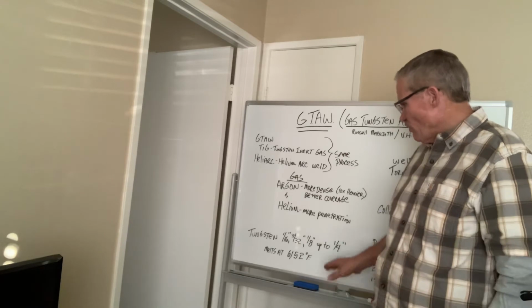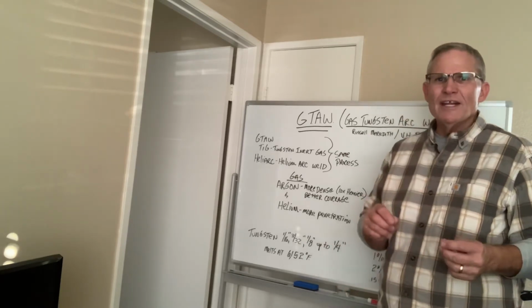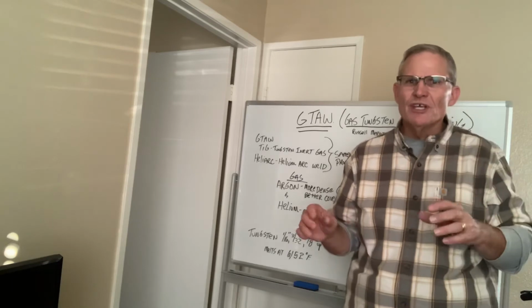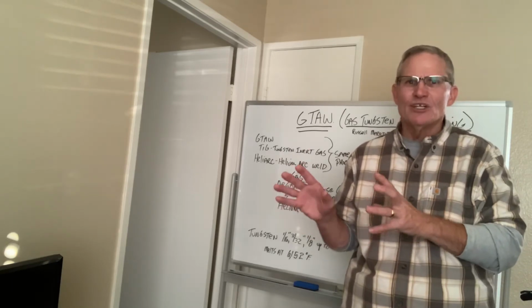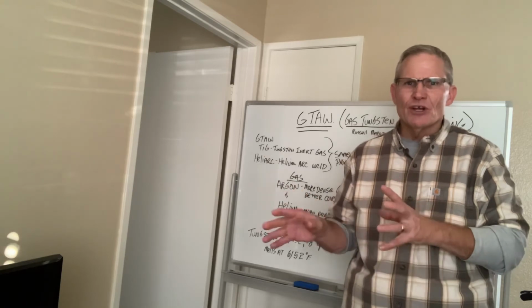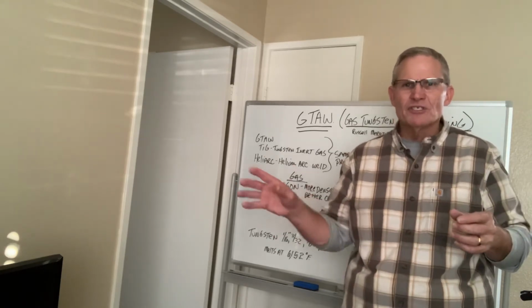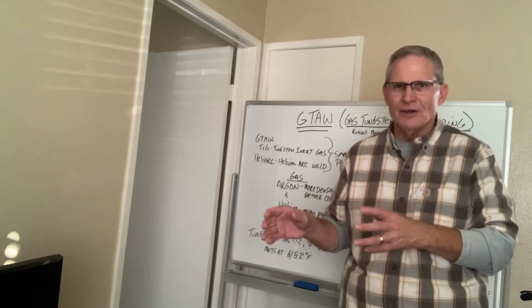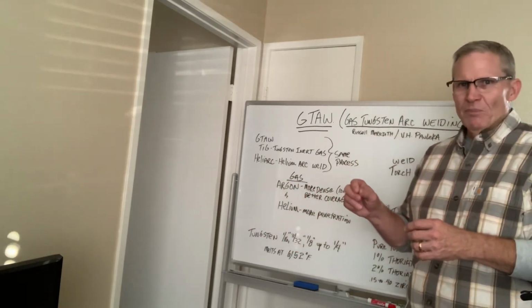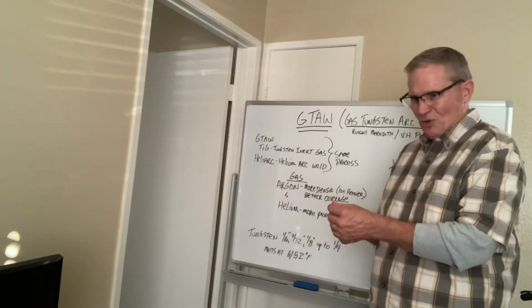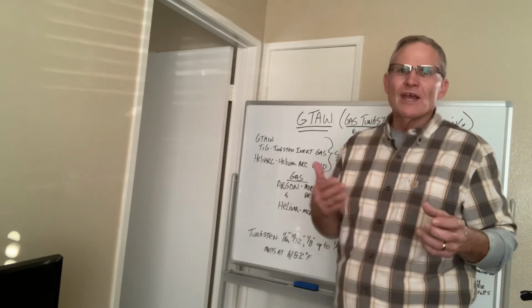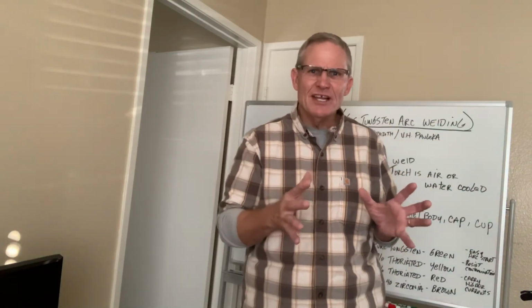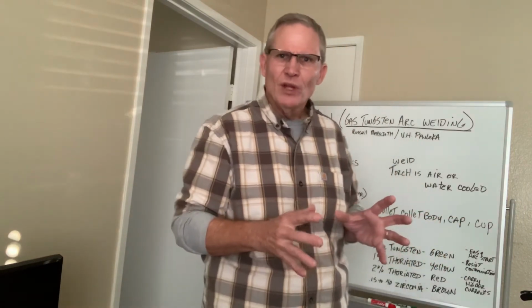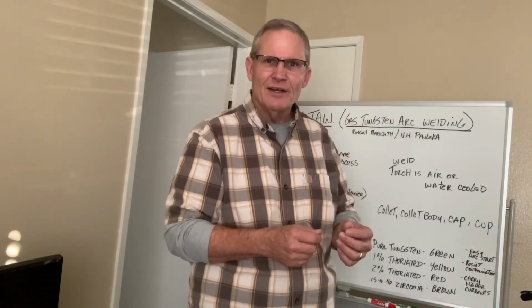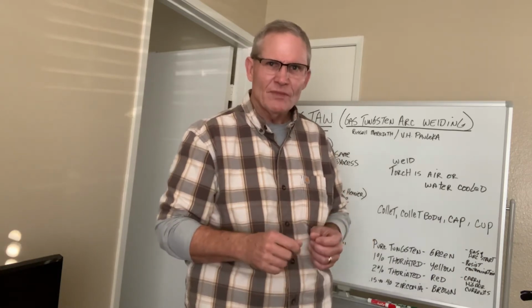That being said, keep in mind, when you're grinding tungsten, make sure you're using a tungsten-only designated grinder. You should not be using a grinder that's used to grind mild steels or other types of steels, because you will grind those other metals right into your tungsten as you're grinding it, and it'll create a sparking effect in the tungsten. So we always designate a specific grinder that's used only for tungsten, and that's where we grind a point on the tungsten itself for the welding.